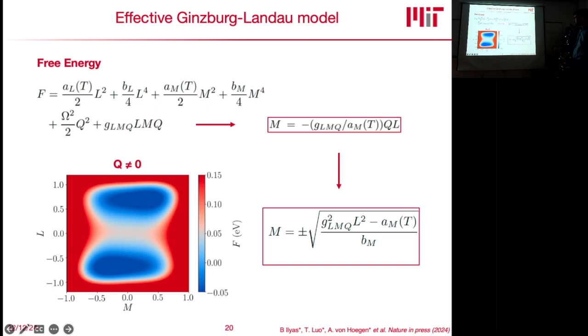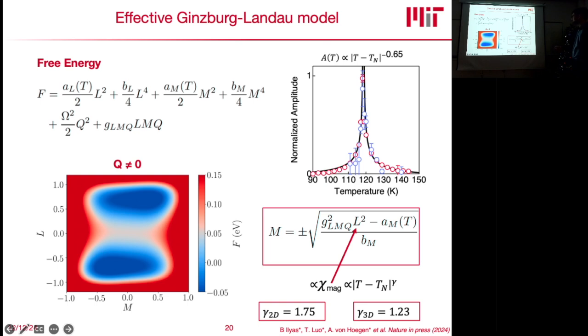And so the magnetization that we are generating depends only on L squared, which is basically proportional to the susceptibility of this antiferromagnet, which again diverges close to the transition temperature. And this is why we would expect something that scales as a square root of this magnetic susceptibility that you can see here. The critical exponent that we find is 0.65. And if you now divide the one that you find for the 3D Ising model by 2, this almost perfectly adds up.